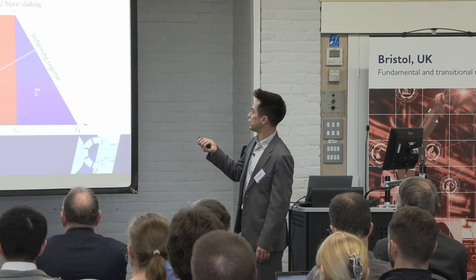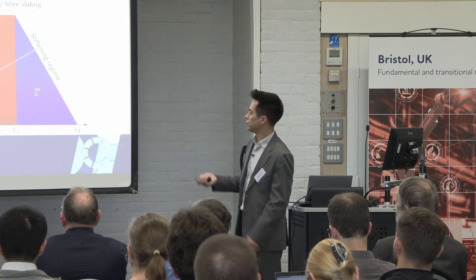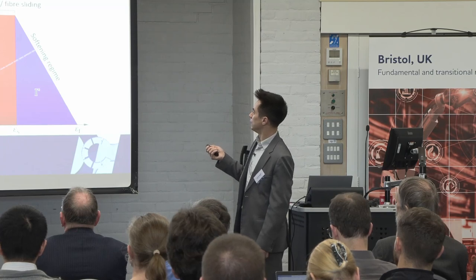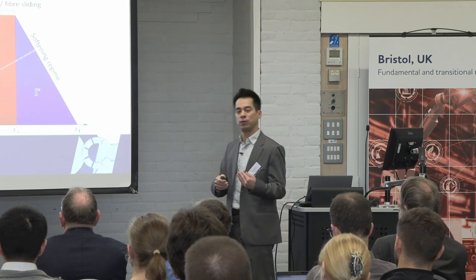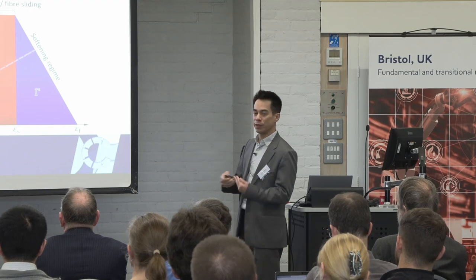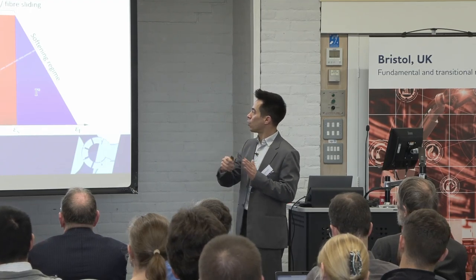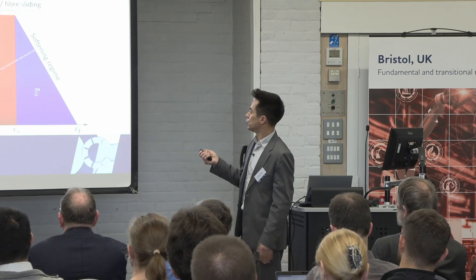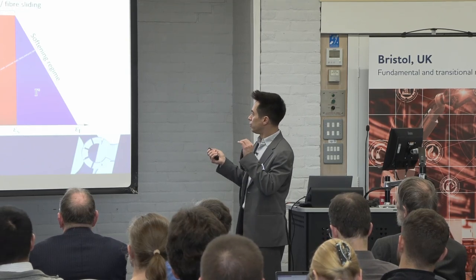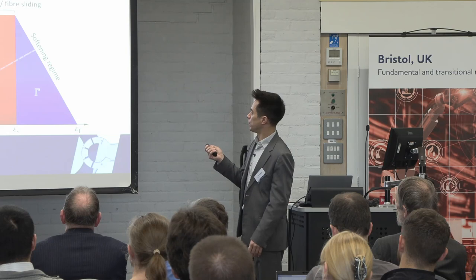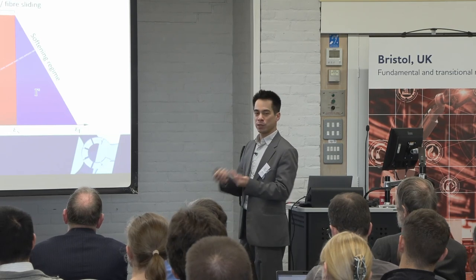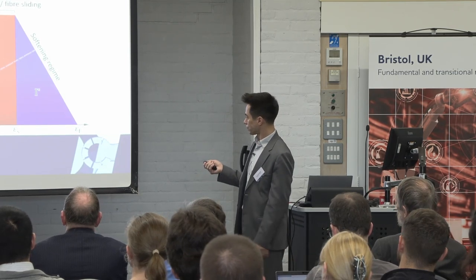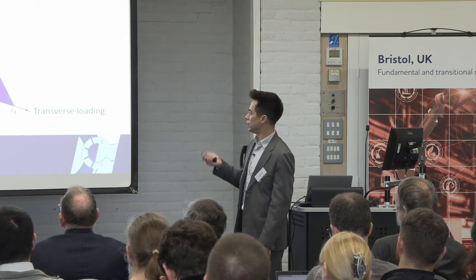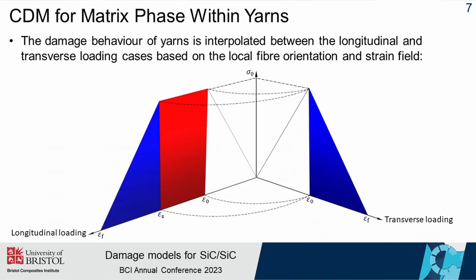However, when we are loading a yarn longitudinally in the fiber direction, the main assumption made here is that the matrix itself, once it reaches its strength, will have a regime of a constant stress. And that is to model the microcracking, fiber sliding, fiber matrix interaction that happens, and the subsequent load redistribution within the material. Okay, and these two are combined in a mixed mode formulation where it can go from transverse loading to longitudinal loading, anywhere in between.